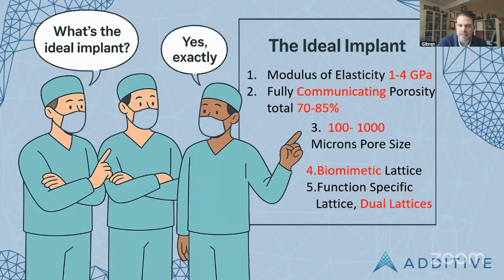The pore size ideally wants to be from 100 to 1,000 micron, and that will encourage early new bone and then stronger bone down the track. We also did a lot of research and development into having a biomimetic lattice. Biomimicry is the science of using what's already existing in nature and replicating that in a structured element. We also identified that potentially using two different lattices distinctly in the one cage to address specific functions could be a good idea. So we've done a lot of research and development into this area, where we have developed two distinct lattices to put into one cage.